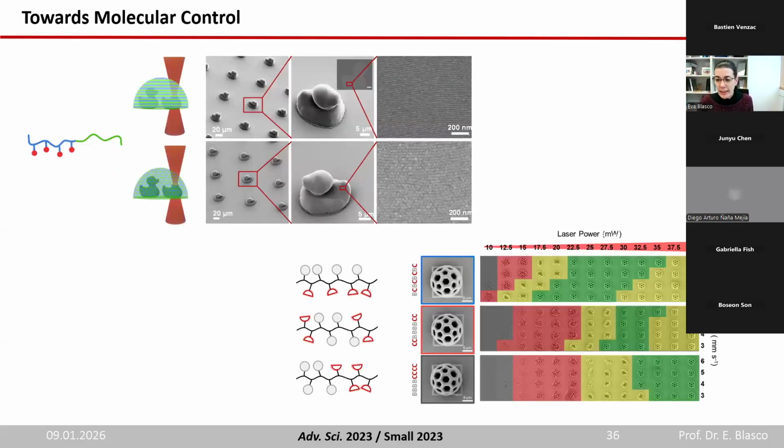So taking inspiration again of natural systems, we have also played with more synthetic systems. Block copolymers can also self-assemble at the nanoscale, and by playing with the length of these polymers, you can also fine-tune the type of nano assembly. So we have some of them that can align in lamella or cylinders, and we have proved that we can maintain this nanostructure inside printed structures. So these were ducts that were cut and analyzed inside, so we can keep large order inside.